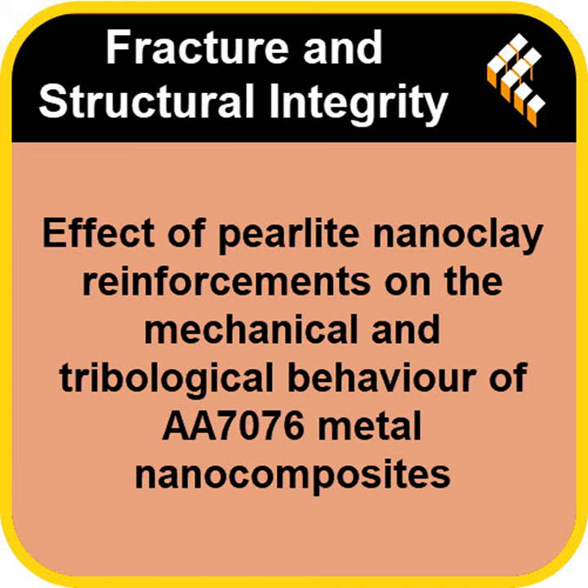Did they look at how the samples actually broke? Did the fracture surfaces confirm that better bonding in the 1.5% sample? They did, and it lined up. The weaker composite, the 1% one, failed with a relatively flat, kind of smooth fracture surface. But the optimal 1.5% composite, its fracture surface was much rougher, more complex. You could see features like dimples, river lines, signs of particles being pulled out. Which means the crack had a tougher time getting through. Exactly. It shows the crack had to work harder, navigate around those strongly bonded perlite particles. Indicates higher resistance to crack propagation, better toughness, essentially, despite the slightly lower ductility. Okay, so it's stronger, tougher surface.